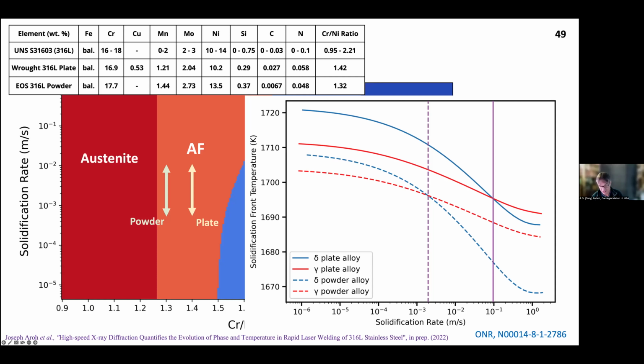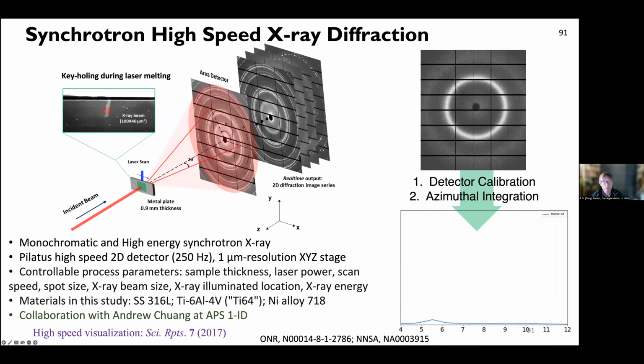Oh yes, that is very much my hope, that we would be able to go back to these maps and look in more detail and say, yes, there have to be dislocations. If that's an indent, there have to be dislocations sitting underneath the indent. And be able to, probably through some kind of forward modeling exercise, reconstruct that network of dislocations and model from there.